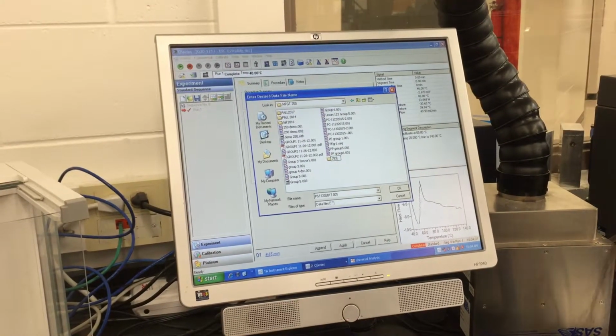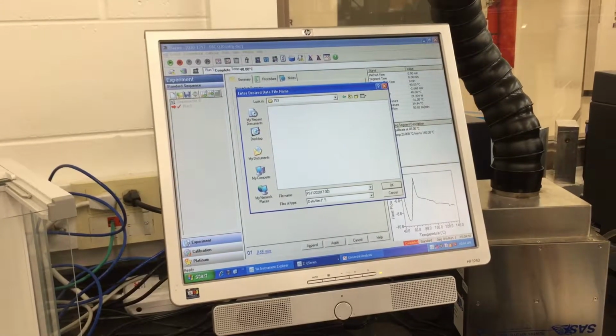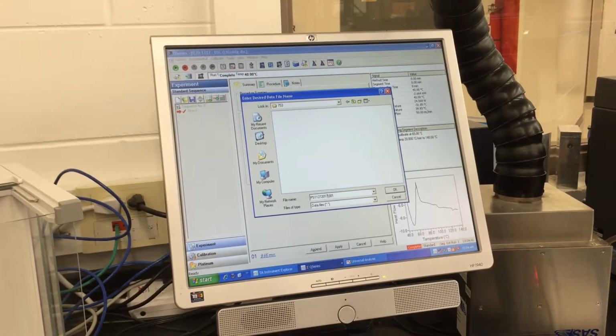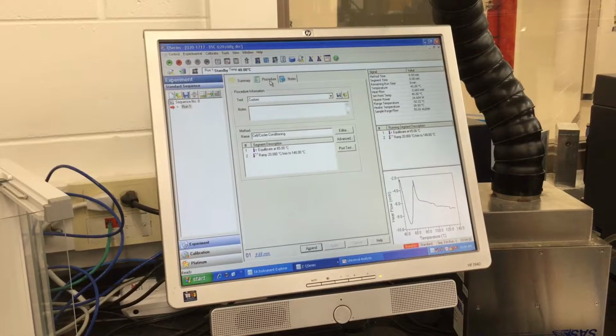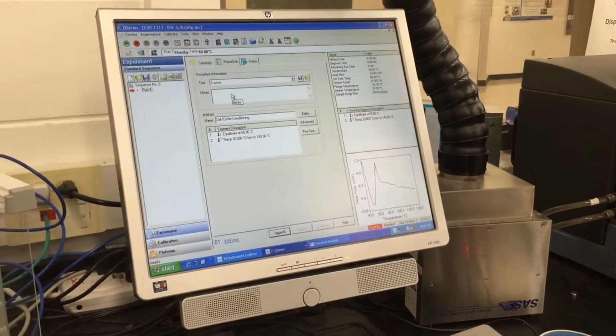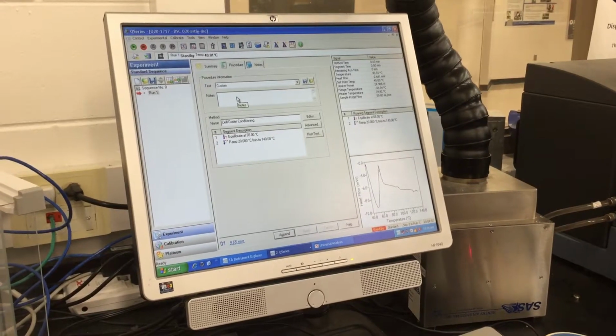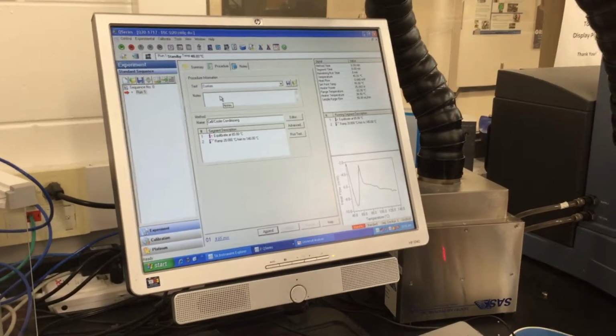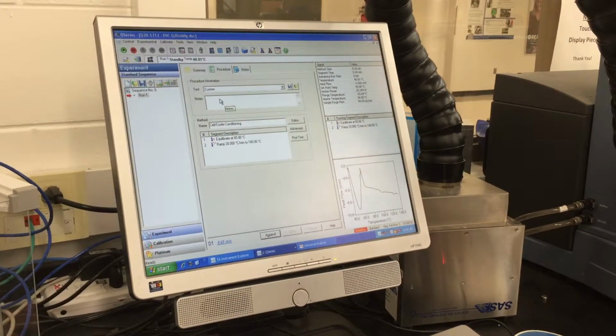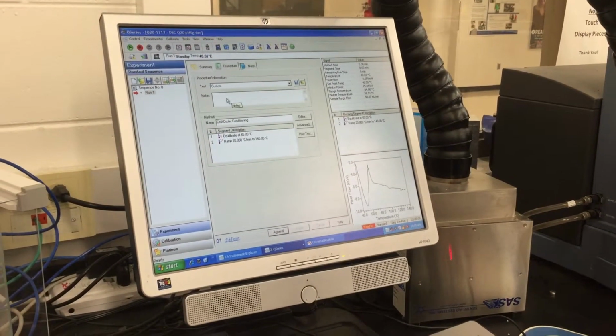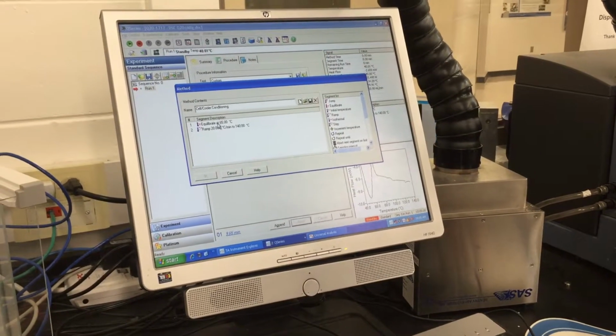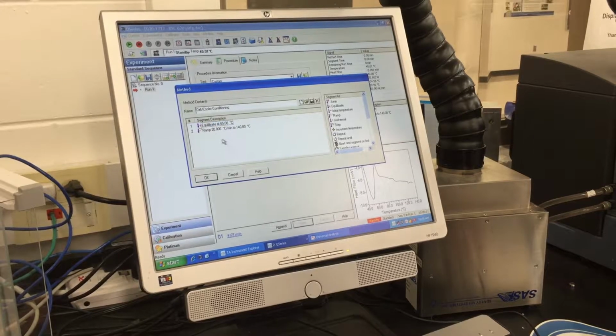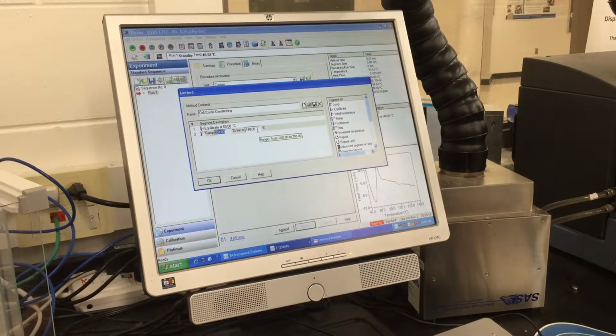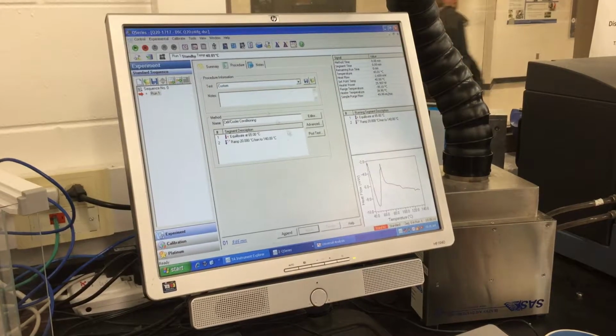Let me make a new one here, called 753, and we click the folder, and we give a file name PS 11/27/2017. Click OK. For the procedure, the DSC is typically used to measure the glass transition or melting temperature or both of the samples. For polystyrene, we want to measure the glass transition of this sample, and I know the Tg is around 100, so we'll just let the sample equilibrate at 65 and then ramp at 20 K per minute to 140 degrees Celsius, and then click OK.